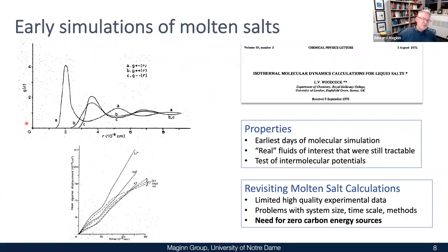Here's what's called the radial distribution function. This is the relative probability of observing two different species at a given distance. And here's the distance listed here. This is really in angstroms. And what you can see are peaks and valleys. And what this tells you is that for curve A, for example, the cation and the anion show a preference to locate next to each other about 2 angstroms apart. A totally uniform distribution of separations would be at a g(r) of 1. So everything bigger than 1 tells you have an enhancement in the local density. And this just tells you the first solvation shell or coordination shell of where a plus and a minus would tend to orient in the liquid.